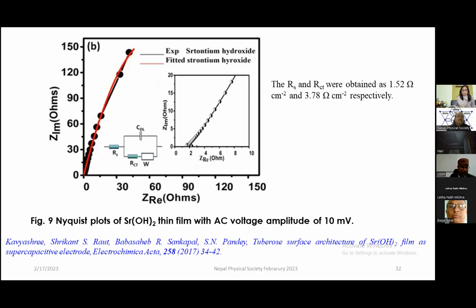Further, we have done the Nyquist plot. Here one can see that we have fitted it, and we have obtained the equivalent circuit given by this one. From this equivalent circuit, we have calculated the values of RS and RCT. RCT is the charge transfer resistance, and in this case it comes out to be equal to 3.78, and RS, the solution resistance, is 1.52 ohm per centimeter square. For a better supercapacitor application, the values of RS and RCT should be small. Here it is comparable, so one can see.